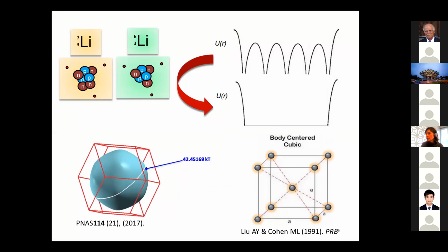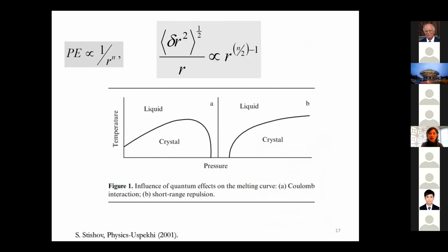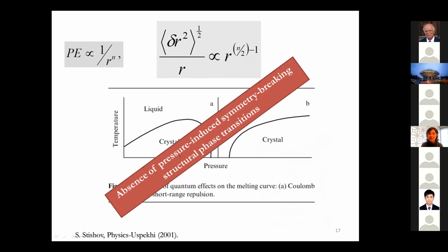And it's also a very simple system at ambient condition. You can approximate it with empty lattice models. It has a pretty well spherical Fermi surface. It has a very simple structure. It has two known stable isotopes, lithium-6 and 7. Atomic physicists love these isotopes because one of them is fermionic and one of them is bosonic, so they can even study the statistics. And then one would say, okay, let's get this lithium, squeeze it, and get this quantum liquid ground state. But the problem is that obviously it's not as simple as that.